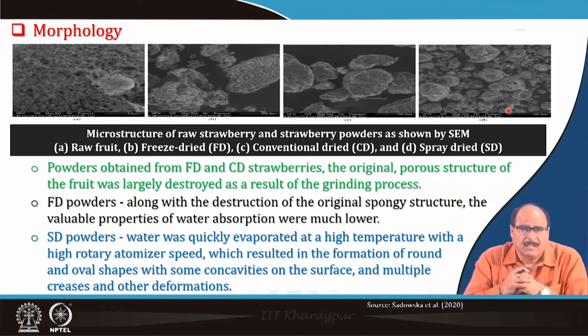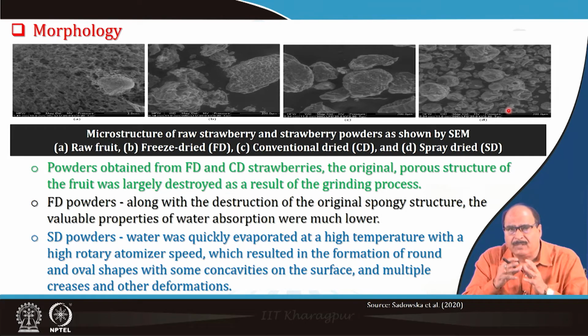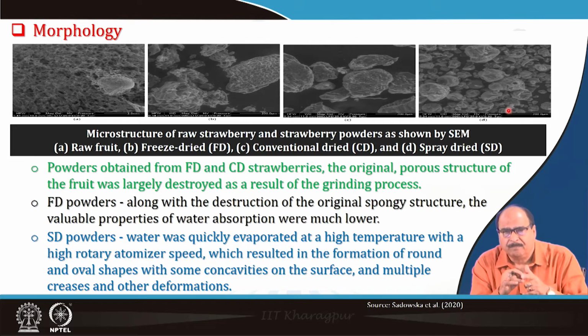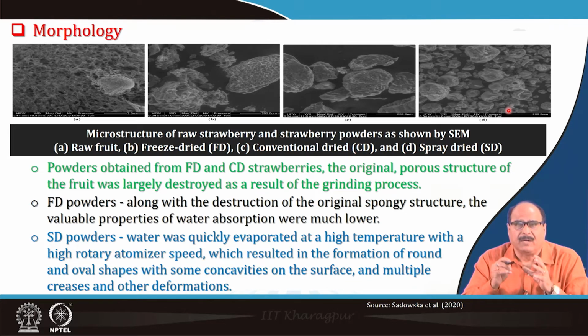Freeze dried powders, along with the destruction of the original spongy structure, the valuable property of water absorption is also affected. Spray dried powder: in the preparation of the powder during spray drying, water was quickly evaporated at a high temperature with a high rotary atomizer speed, which resulted in the formation of round and oval shapes with some concavity on the surface, multiple creases and other deformations.